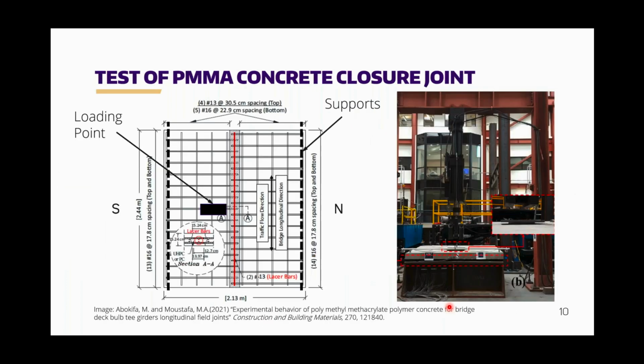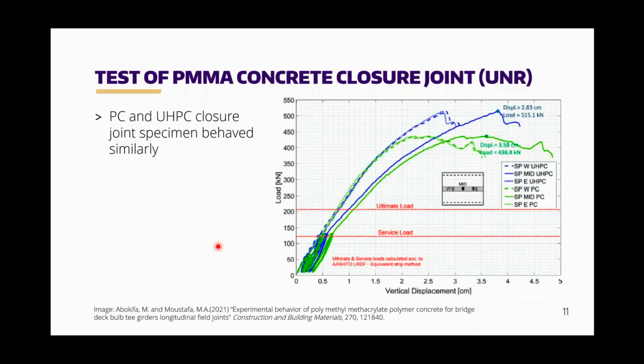We also have some testing done as part of the ABC-UTC at the University of Nevada, Reno. So this was some testing done by Muhammad Mustafa, and they looked at some precast deck panels and a closure pour between those two. And they compared UHPC and PMMA, or polymethyl methacrylate polymer concrete. And they had a simple setup here where we had 2 precast deck panels, lines of support, and they had a loading point there at the midspan. And to compare those 2 curves, I'm showing you the load in the actuator versus the vertical displacement at either the midpoint or a point adjacent to the midpoint. And the green curve in this case is the polymer concrete, the PMMA concrete, and the blue curve is UHPC.